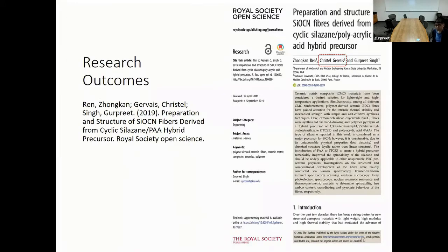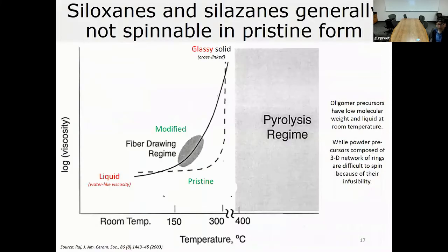Before I get to what this paper is about, I think it's important to mention that many of these multi-component pre-ceramic polymers are either siloxanes or silazanes. And a lot of these low-cost, commercially available siloxanes are liquid phase at room temperature, and these are essentially oligomers with viscosity similar to that of water. So if you try to draw fibers from it in its pristine form, it's just not possible. The rheology is poor, so the rheology needs to be modified. And we can achieve that. There are many ways to do that.